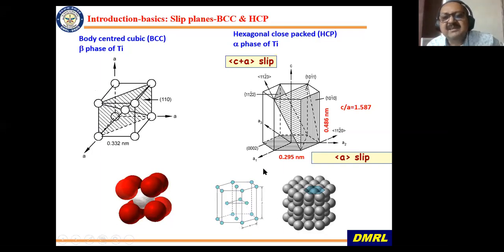And if you look at the slip planes, this is the basal plane, and you have these 3 directions which are close packed. So the basal plane is called either 0001 or, normally, 0002. And then this is called a prismatic plane. This also has a close packed direction in it. And then you have these 2 planes which are known as pyramidal planes, and you have the C plus A kind of slip there,